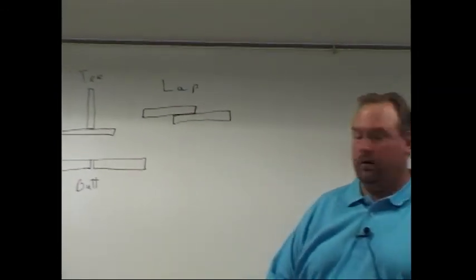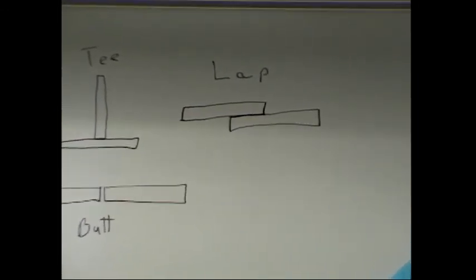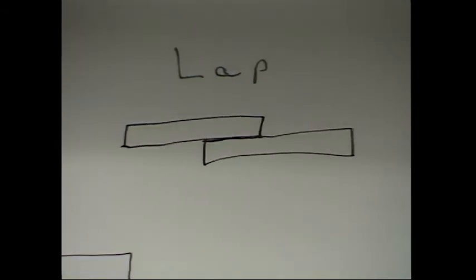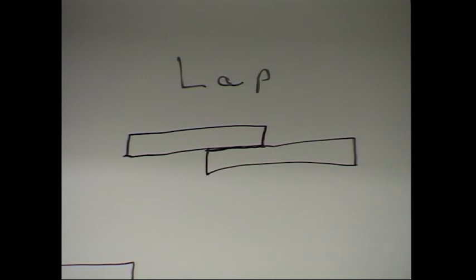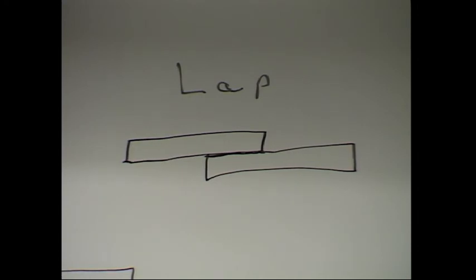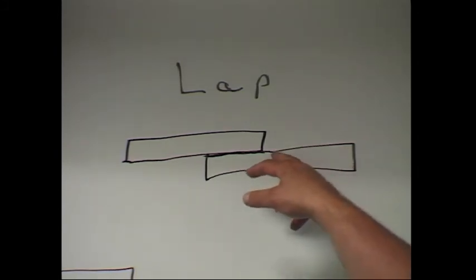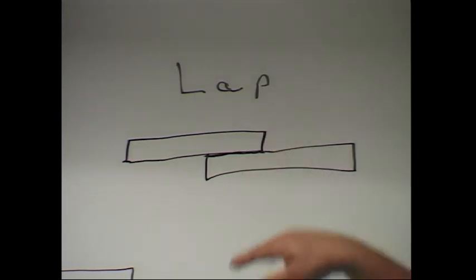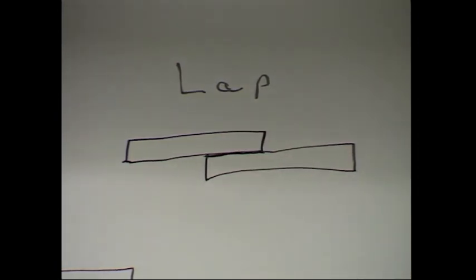Okay, welding a lap joint, like this one up here. You're actually using what's called a fillet weld. In other words, you're welding in a corner up there. You'll be welding it right here. Sometimes it's hard to get down in the corner with the oxyacetylene. So if you're looking for maximum strength, if you can do it, you probably want to weld it on both sides of the lap, okay? That will also prevent it, because if you only weld on this side, the weld is going to start shrinking and actually pulling it apart on the backside. So if you can weld it on both sides, that'll give you maximum strength, and that's the most desired, but in a lot of applications, you might not be able to do that.